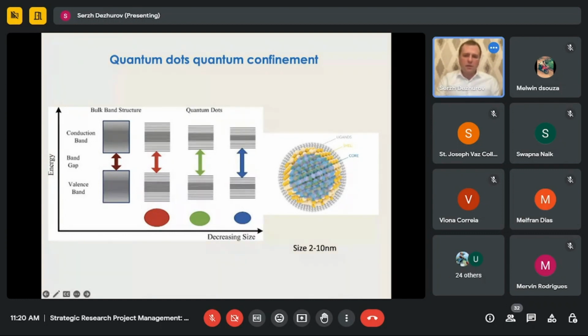Our energy levels are quantum confined, and they change from bigger sizes to small sizes. These energy levels become wider. In bulk structure, there is no quantum confinement, so you can't see any luminescence from bulk semiconductors, not like from quantum dots, because these discrete levels of energy produce a strong line of fluorescence in part of the spectrum that's connected with the size of these nanoparticles. The biggest particles are more red, and the small particles are blue.